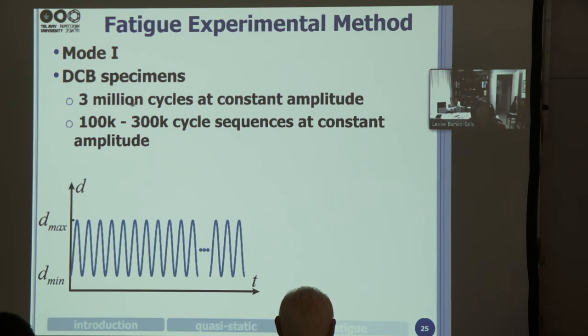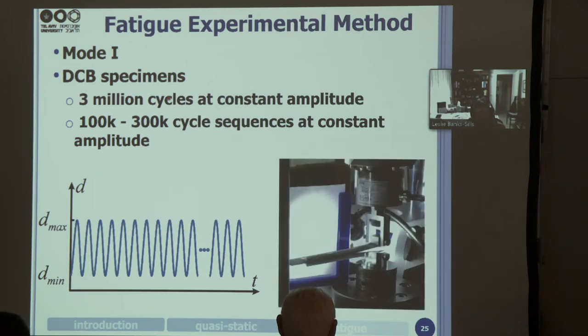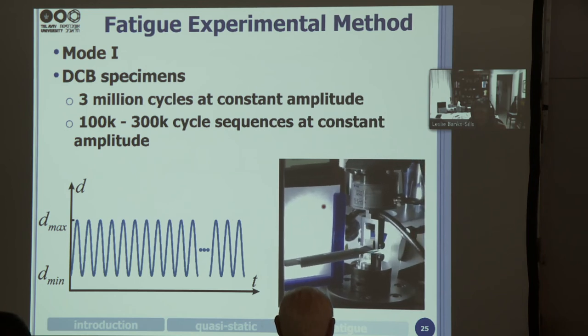And let me just say that the specimens that were cycled at 3 million cycles ran for about 9 days continuously. Automatically, we take pictures even in the middle of the night when we're not there. And here you can see the specimen that's connected to the load cells in the Instron loading machine. And we have all kinds of ways of taking pictures. We need to use light sources and so on. So here you can see the test as it's being carried out.